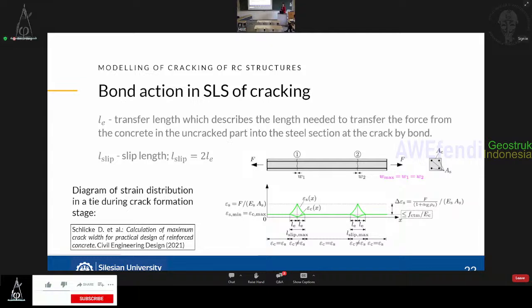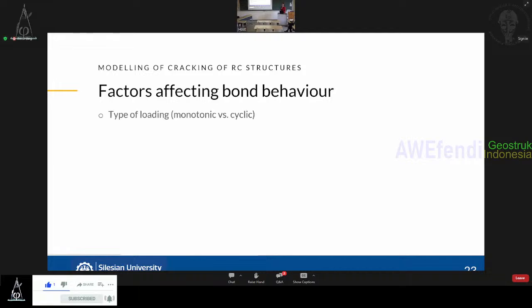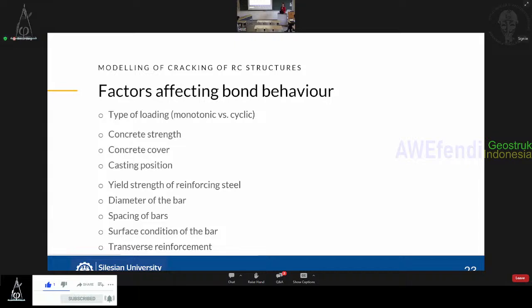Of course, the slipping length would depend on the bond properties between steel and concrete, specifically the bond stresses, which depend on many factors. These factors include the type of loading, the properties of concrete, such as its strength, the concrete cover, casting position, and some properties which are related to the reinforcement itself, like its mechanical properties, diameter of bars, spacing of bars, surface condition of the bar, so whether we have, for example, a plain bar or a ribbed bar, and whether we have any means of confinement in the form of, for example, transverse reinforcement.